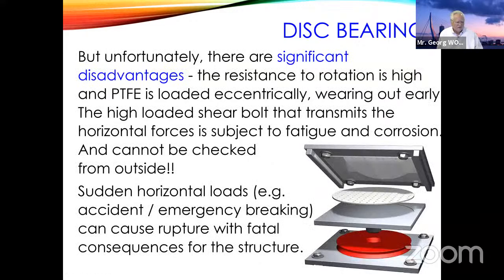But this bearing makes a lot of problems. It has significant disadvantages. The resistance to the rotation is very high. You know, this disc is not as soft as the rubber. You need a big force to rotate, and that gives eccentric loading to the PTFE, and then the PTFE is wearing out much quicker. And this bolt in the middle, which is transferring all the horizontal forces, is subject to fatigue and to corrosion, and it cannot be checked from outside. So when you have sudden horizontal loads, e.g. for a railway bridge you have emergency braking, or in a road bridge you have an accident on the bridge, then it can happen that the bolt is breaking suddenly and you have no more safety for the horizontal forces.